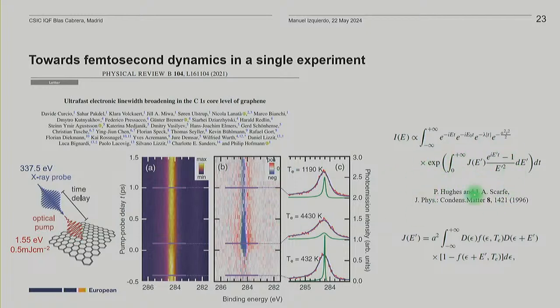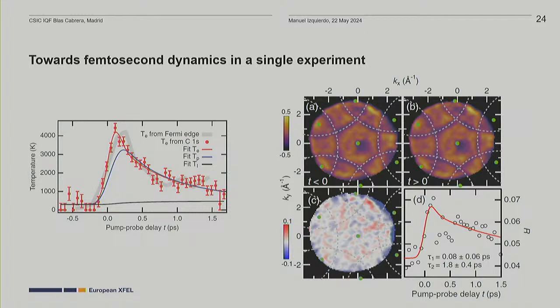So basically they realized that they had to modify this because the system in principle was so hot that you cannot just consider that you only have interactions from below the Fermi energy to above, so you can also have a recombination and recoil and all these things from excited electrons. And basically what they managed to do is to fit this. The blue is the fitting, and the green represents the electronic temperature. Then they plot this as a function of time, and they saw that at the very short time delays, the electrons in the system can be as high as 5,000 Kelvin.